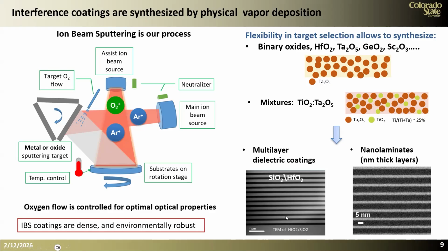I show you here pictures of transmission electron micrographs of a multilayer of silica and hafnia. And what you can see here is that the interfaces between the two materials are very sharp. And we need that to have a good contrast and tailor the optical response.